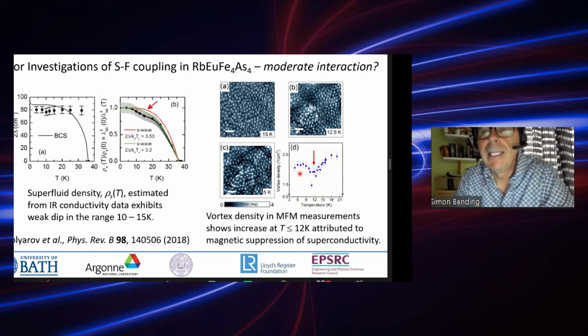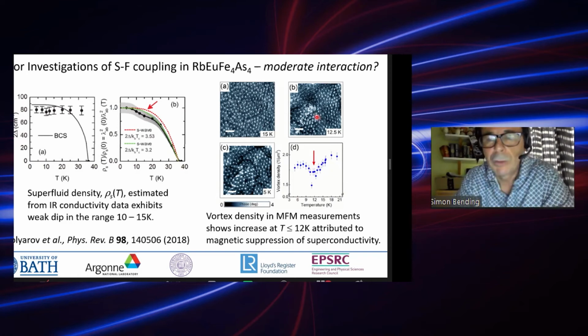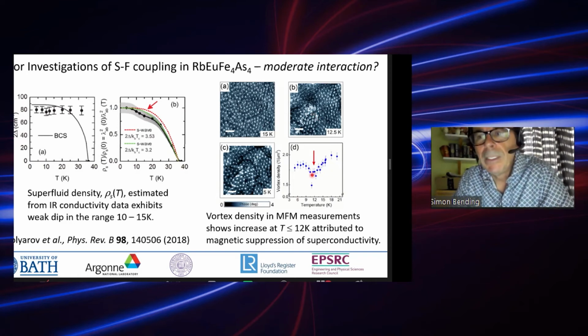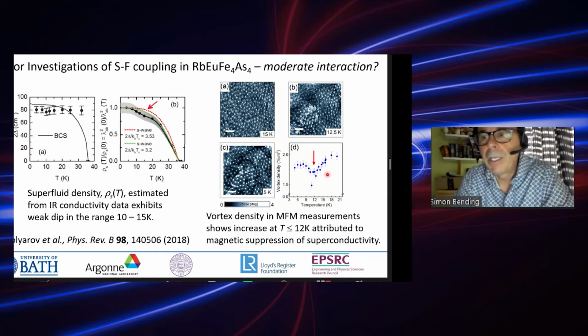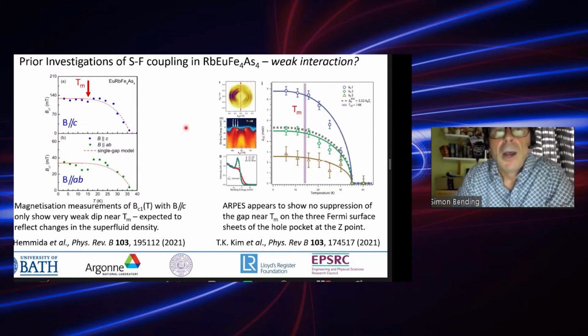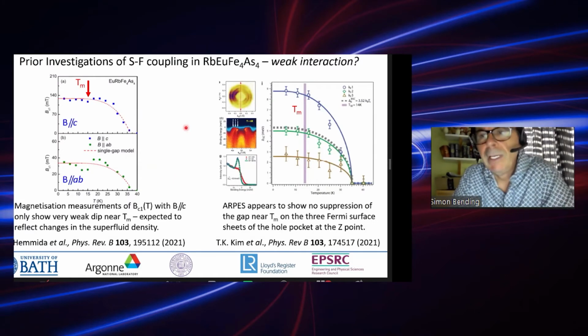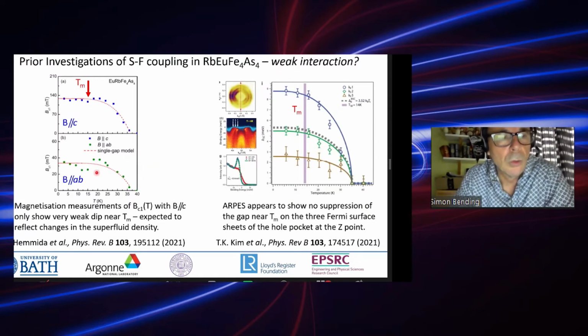The MFM data are also quite interesting. You can see down here, this is the density of vortices as a function of temperature, which has been plotted, extracted from these images. And below about 12 Kelvin, you actually see a slight increase in the vortex density, which again is attributed to magnetic suppression of superconductivity. So these are examples which seem to show not strong, but at least a moderate interaction between the magnetic and superconducting systems. On the other hand, there are other experiments which really don't seem to show much interaction at all.